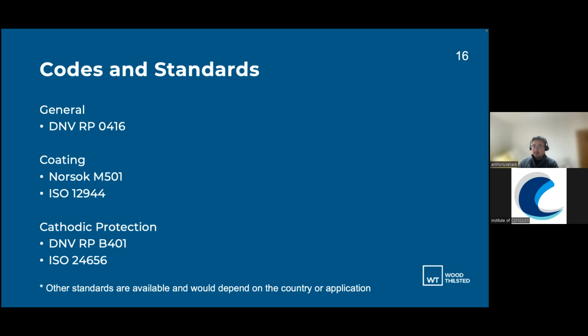and they're all spaced roughly 1 to 2 kilometers, 1 to 2 nautical miles from each other, and that proximity can increase the seawater velocity as it goes through the monopile, and the monopiles are generally quite large. They are looking at about 10-meter diameter. So when the seawater hits that, there is an increase in the velocity around, and that affects the current density for protection. As I said at the bottom, there are other standards available. It would depend on the country and the application.